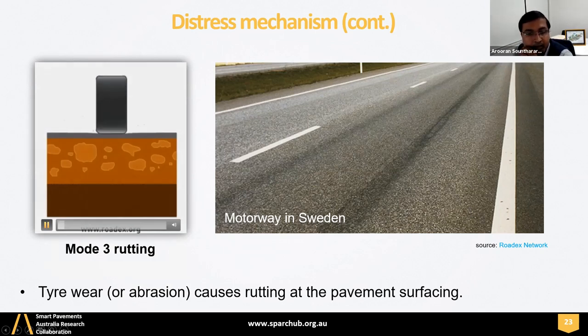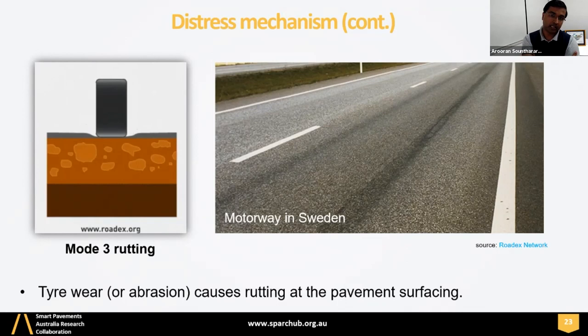Mode 3 rutting is an example from Sweden, taken from the Roadex Network. This type of rutting occurs due to tire wear at the surface, or abrasion. And this type of rutting needs immediate maintenance, because if the impermeable layers become permeable, water gets into the pavement. Right? So this type of rutting caused by tire wear needs urgent repairs to prevent water getting into the pavement. As I indicated earlier, water is the enemy, because water creates more damage to the pavement under traffic loading.